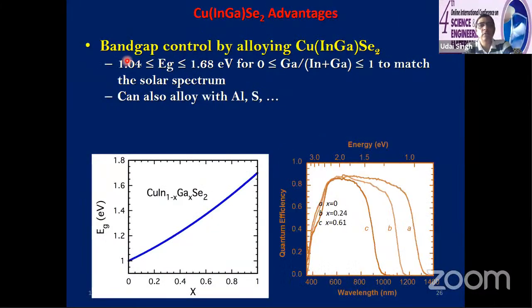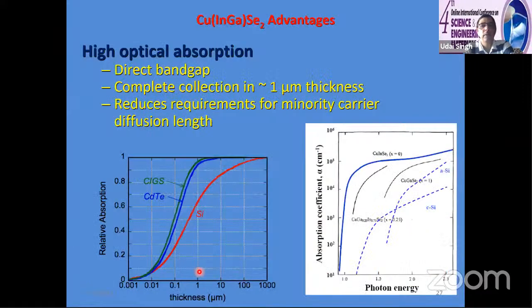I already told you this band gap variation is possible. I will just skip this. And on the absorption coefficient, you can see if you want to absorb more than 90% of light, for crystalline silicon, which is indirect band gap, you need more than 100 micron thick material. But for copper indium gallium diselenide or cadmium telluride or CZTS, copper zinc tin sulfide, one micron is sufficient. But when you try to deposit 1 micron, you always get certain pinholes. So people try to maintain between 2 to 3 micron.